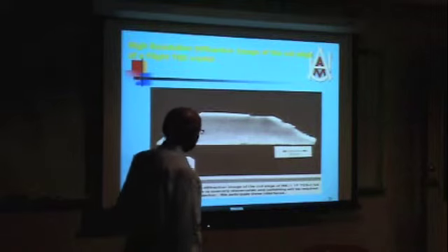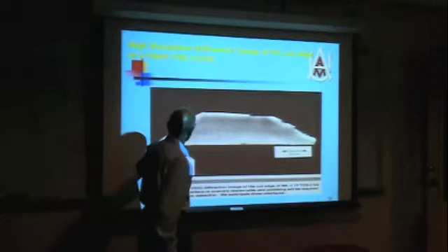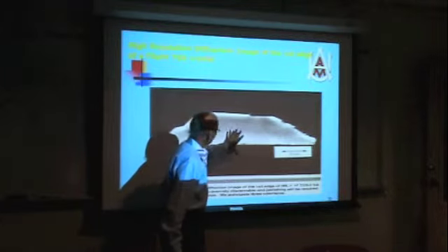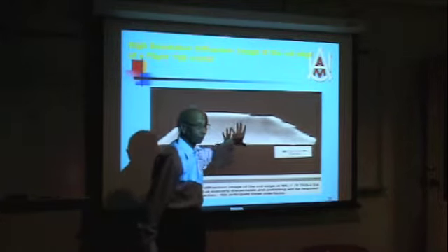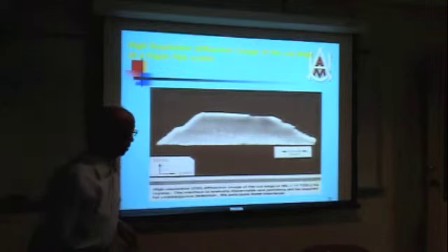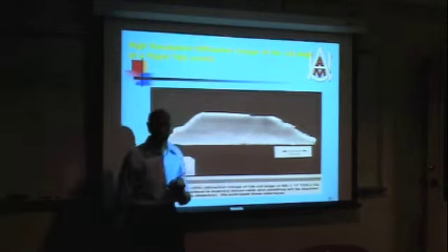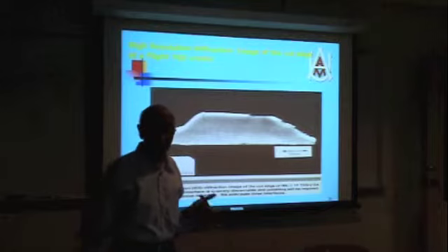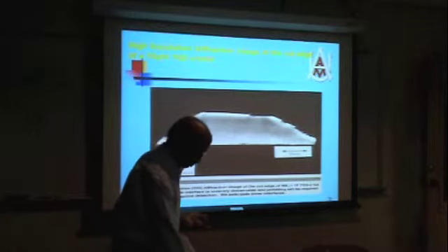This is a crystal which is cut from the flight grown crystal. The seed crystal is somewhere here. But when we cut a slice and looked at the topographic picture by X-ray techniques at Brookhaven National Lab, we could not see a demarcation line where the seed is. So that shows that diffusion was predominant there, there is no convection.